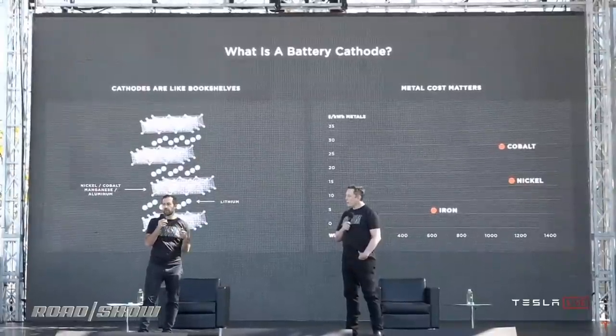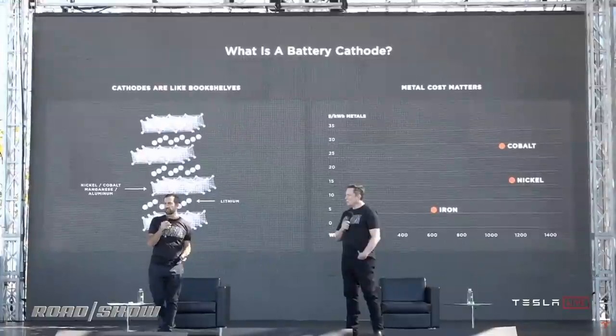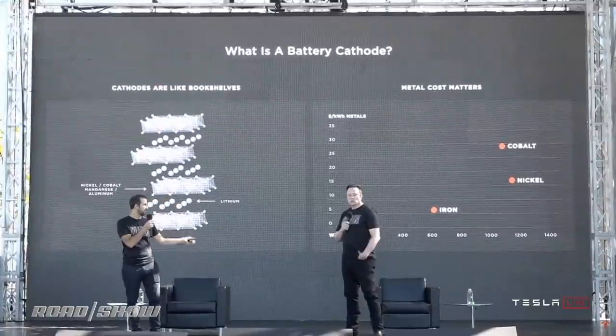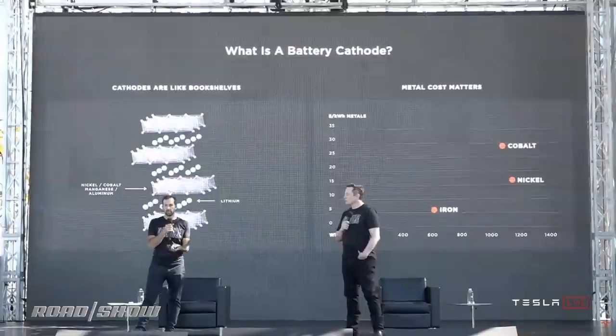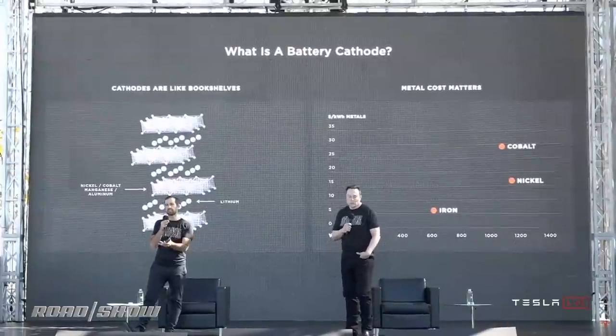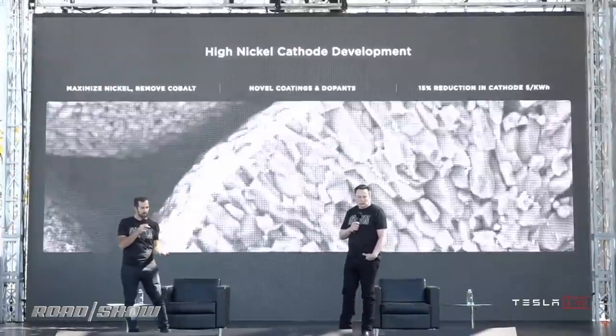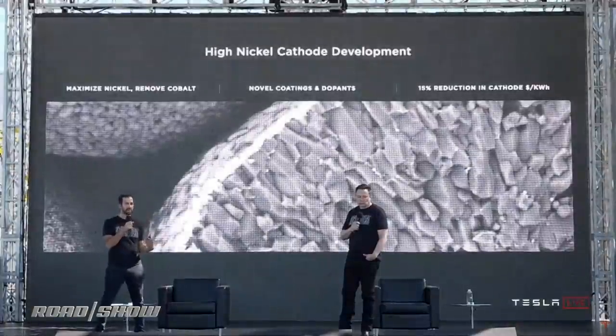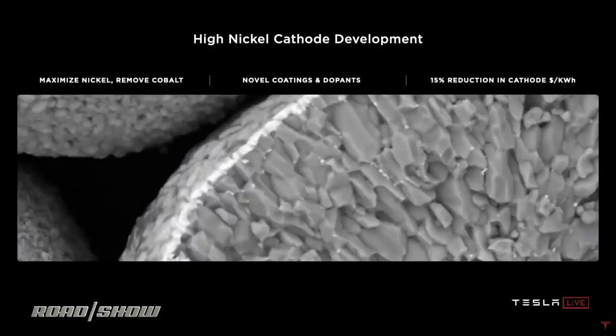But one of the reasons why cobalt is even used at all is because it is a very stable bookshelf. And the challenge with going to pure nickel is stabilizing that bookshelf with only nickel. And that's what we've been working on with our high nickel cathode development, which has zero cobalt in it. Leveraging novel coatings and dopants, we can get a 15% reduction in cathode dollar per kilowatt hour.